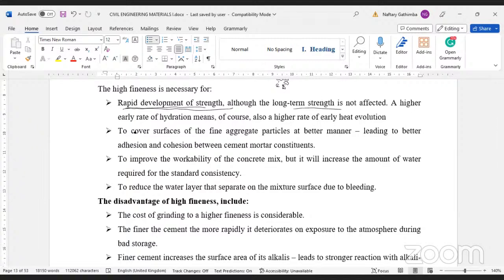Okay, we may also want cement to be fine, because you see, concrete is composite in nature. That is, we have coarse aggregate, we have fine aggregate, and we have cement. So we need cement which is fine enough so that it can cover all these aggregates, including the fine aggregate, that is sand. We need our sand to be covered by the cement slurry. That's why it has to be smaller sized than the fine aggregate itself. And again, our concrete mix is more workable. We are able to work on it quite well when the cement paste is fine.